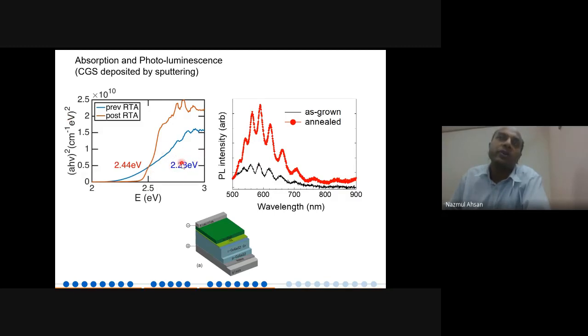So here I show you that if you have less sulfur, then your band edge goes shallow with a very slow rise, and it tells that your quality is not good. You have a lot of states below the conduction band, and you don't have a good band gap. But if you have sulfurization of your thin film, then the band gap becomes sharper and sharper, and you have the least amount of band gap defects. So right now we are working on how we can reduce the amount of states below the band gap and make the band gap sharper. And this tells photoluminescence.